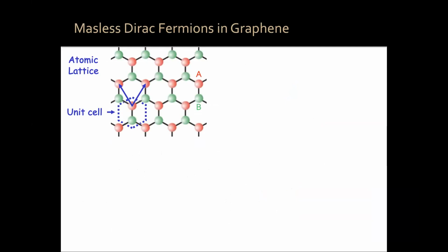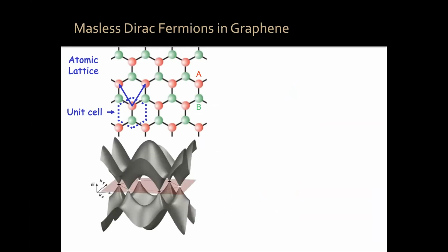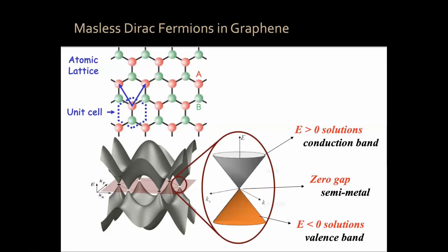Now you can calculate the electronic structure of electrons in graphene, a simple model. Okay, and you get energy versus momentum in the x and y direction. And it's this very unusual electronic structure where near the Fermi energy, you have a linear energy momentum dispersion. That's unlike most solid state systems where you have a quadratic or parabolic energy momentum dispersion. And this, already from the beginning of graphene, led to all these analogies between electrons in graphene and massless, ultra-relativistic particles in high energy physics.